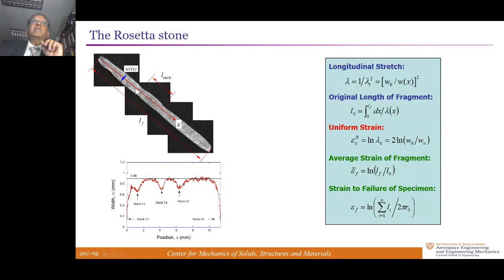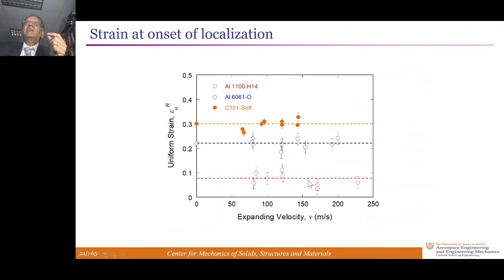So if you measure the width of this and call that W of X along the length, you see there are regions in which this width is constant, which means it hasn't strained beyond a certain point. This is plastic deformation. It's incompressible. So you can take that width variation and convert it into axial strain of the specimen at that point. And what it says is, in pieces of the specimen in between where the necks are, the strain is uniform. The magnitude of the uniform strain can be calculated simply by knowing the width variation, and that uniform strain is constant.